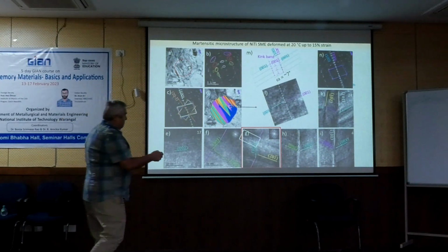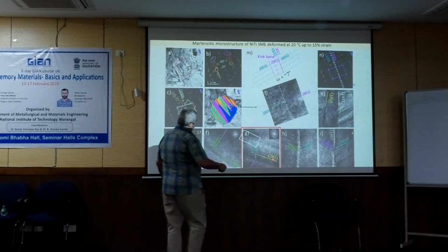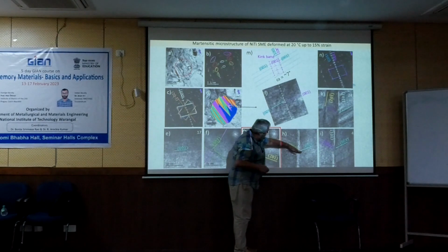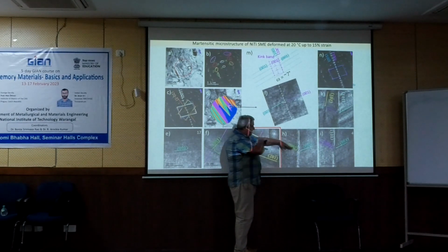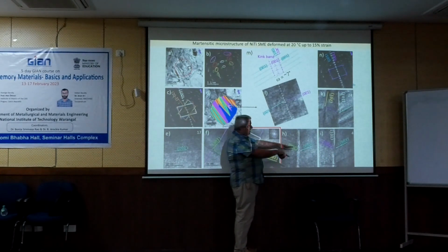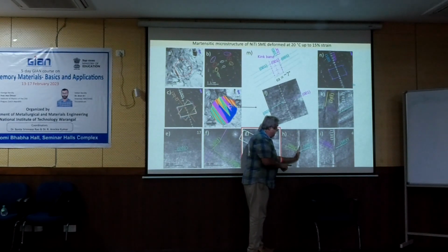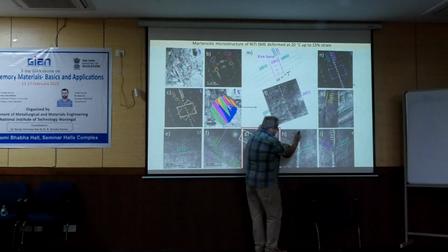And because the strains on the sides of the interface are shears along this plane in this direction, and here I have shear along this plane in this direction, the compatibility means that this will be a mirror symmetry.